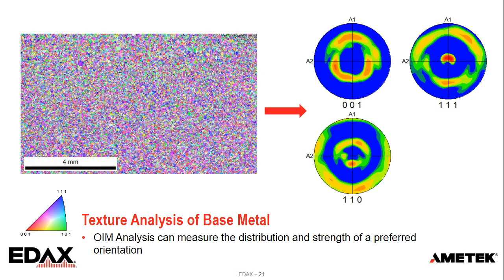That's why when we look at that region, there's a good amount of blue. And if we had the scale bar, we'd be able to tell how much over random that distribution is. We can see it's sort of annular around that. It's what we'd generally call a fiber texture, at least close to a fiber texture. It's got some funny shapes to it. But we can see it's more randomly distributed around the clock face of that 111. So that's what texture can show us.